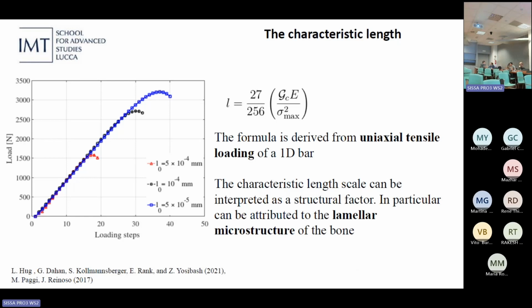Let me just talk very briefly about the main character of the story, which is the length scale parameter here, which was obtained for this kind of simulation basically through a kind of trial and error procedure, because the only known parameter that we know is the maximum peak load. So doing a sort of parametric analysis, we found the L that gives the closest value of the peak load to the experimental results. This parameter can be interpreted in this framework as a structural factor.